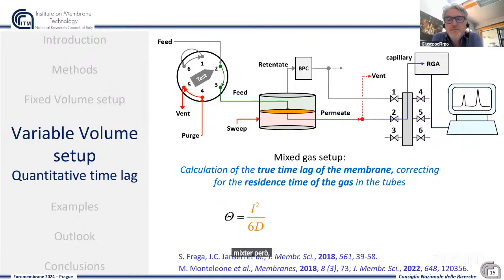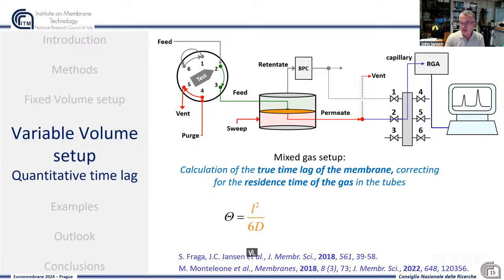Well, at that point, we decided, no, we need something better. We still need to look at the transport through the membrane, but we want to see that with gas mixtures, and that means you need to make two changes. One is you need to take a setup like this one, where from one side you can feed a gas mixture, and from the other side, with or without a sweeping gas, you get a mixture through the membrane. And then you have to analyze the composition.